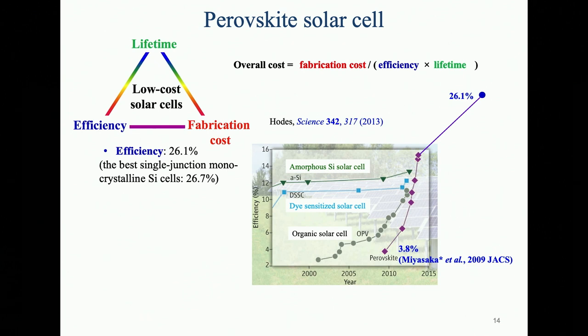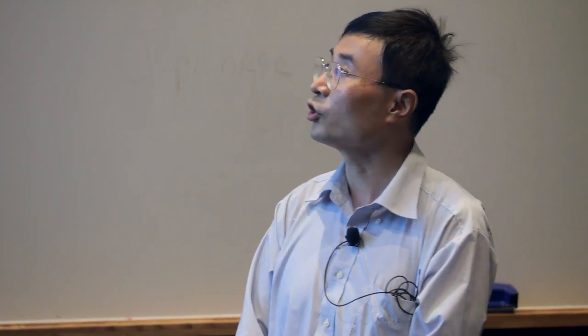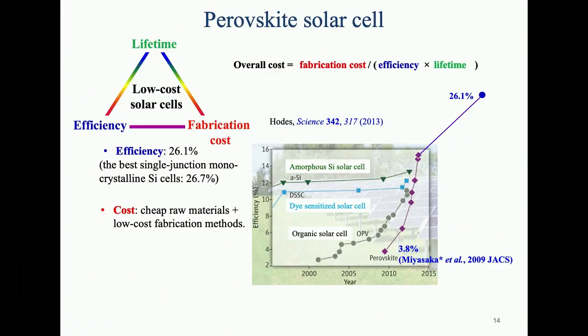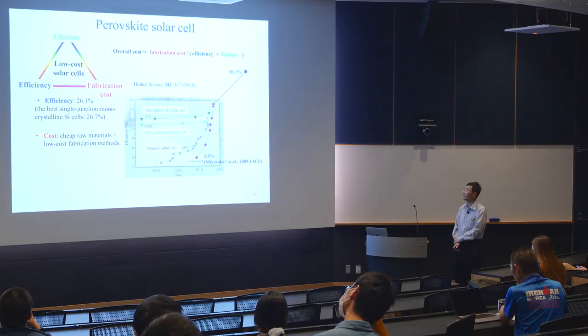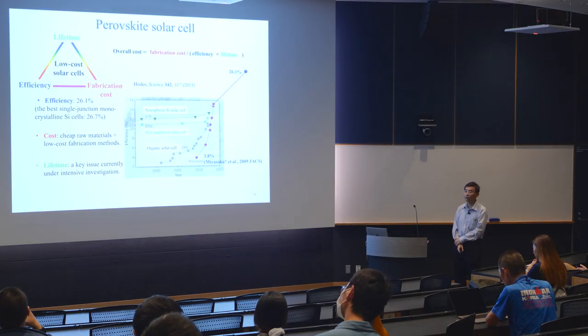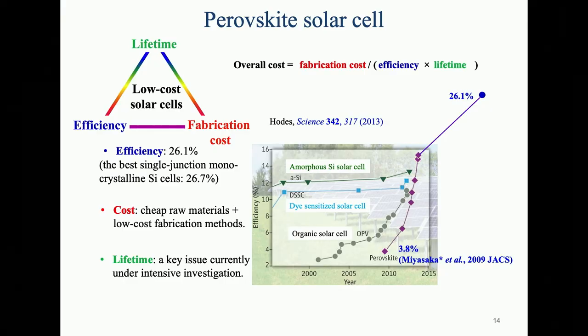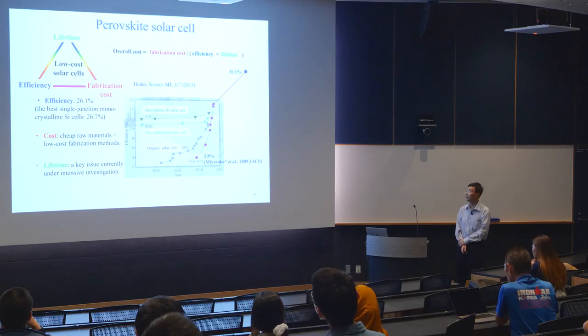First of all, over the past 14 years, the efficiency of perovskite solar cell has increased from the initial 3.8% reported by Professor Miyasaka in his 2009 JACS paper to nowadays exceeding 26%, which is already on par with even the best crystalline silicon cell. While a crystalline silicon cell requires expensive and also energy-intensive processing to fabricate, perovskite solar cell can take advantage of many low-cost fabrication methods. But perovskite solar cell is still facing a key challenge. That is, these cells often suffer from fast degradation and a relatively short lifetime. And this is a key issue currently under intensive investigation by many research groups, including ourselves.